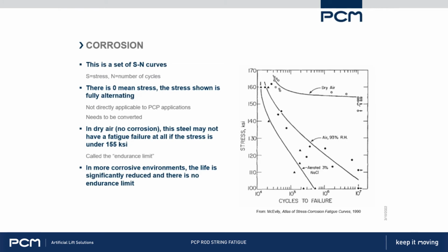It's quite common in steel, when there's no corrosion involved and when the loading is fairly simple, like pure bending, that if you keep the stress below a certain limit, you'll never get a fatigue failure. So in this case, we're seeing that at about 155 KSI. If we keep the stress below that, it could last forever in that particular application. As soon as you get corrosion involved, now we don't see that anymore.